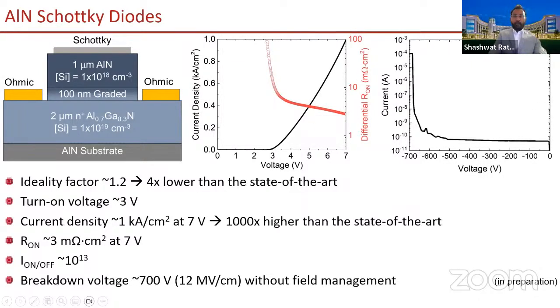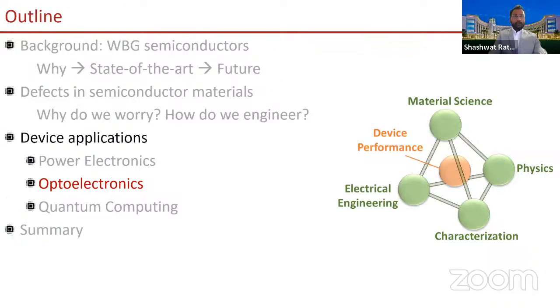And if you look at the off state, using only 1 micron aluminum nitride, we could block about 700 volts, which translates to 12 megavolt per centimeter electric field. And this was done without any dedicated field management. So this only underscores the performance of aluminum nitride based technology. So these are very exciting results, and we'll be publishing this very soon. So this was all about power electronics and where I see this field progressing moving forward.